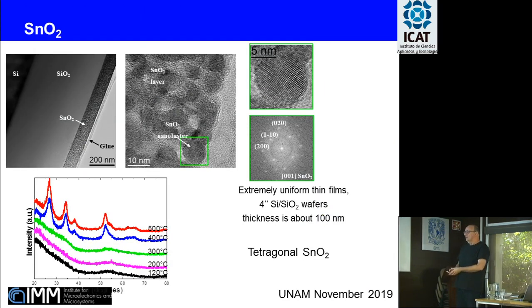You can use them under air without any kind of control of the atmosphere. What is the result? It was very satisfying. You can see how uniform a thin film was obtained by using this precursor. It was nanocrystalline. We can easily see the tin dioxide grains composing the layer, and the crystallographic phase was the typical tetragonal for tin dioxide.